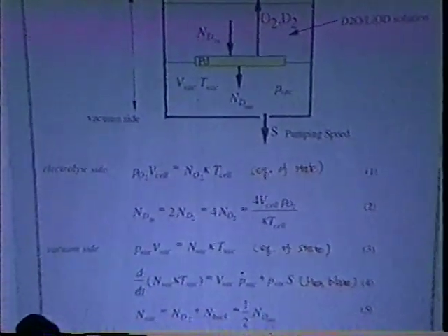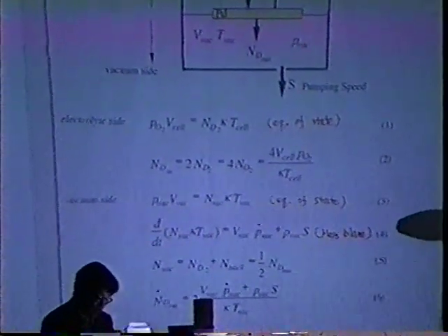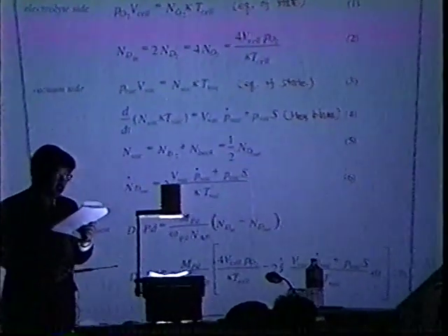Let us move on to the next point. D/Pd analysis is as follows. For the electrolyte side, only one basic equation is applied, and we can calculate the number of deuterons into the palladium by equation 2. As for the vacuum side, the equation of state and the mass balance equation are necessary. Combining equations 3 and 4, we obtain equation number 6. Then the D/Pd ratio is estimated by equation 7, like this.